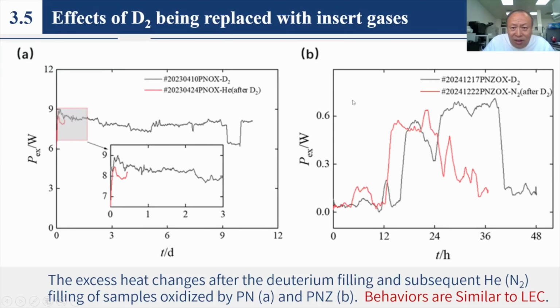This is another effect. When we use inert gases replacing the working gas, which is deuterium, there the excess power exists again. It does not disappear. Of course, the first time, it only lasted about half a day. Secondly, we repeated the experiment, and we can find for the first time, the black one, there is excess power, and then we used nitrogen gas to replace the deuterium. There is also excess power. Of course, after 2 days it decreases.